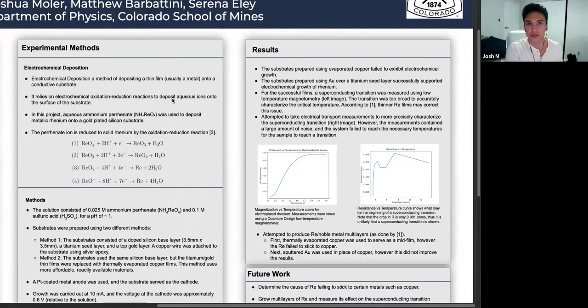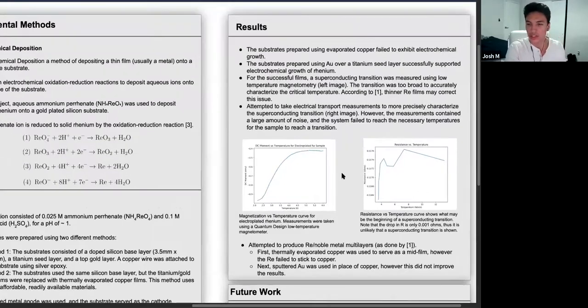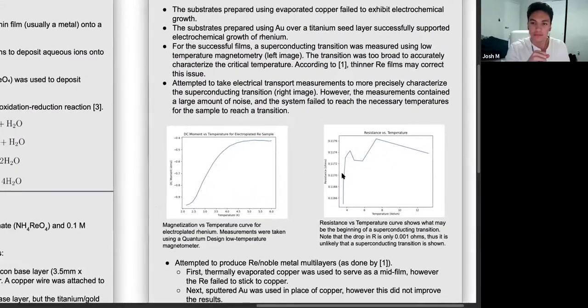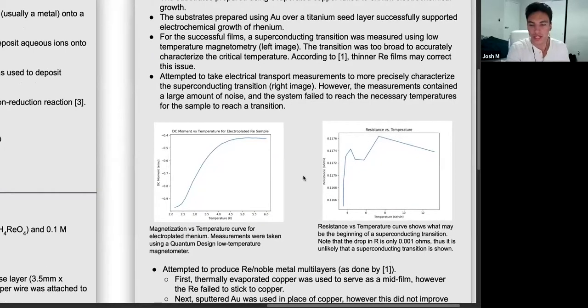So then we resorted to what other groups have used, which is a titanium seed layer over the silicon, followed by a layer of gold, and then you electroplate onto that gold. We had some success doing that. We were able to grow superconducting films of rhenium. We characterized those films first using low temperature magnetometry, which is shown in the image on the left. One of the issues with this was that we ended up getting a really broad transition, which is definitely not ideal for this kind of material.